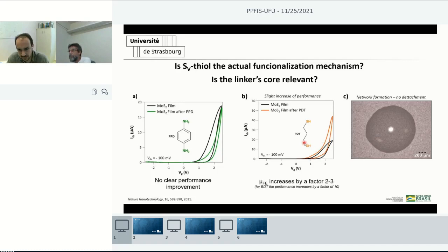And molecules with this PDT, that have the two thiols but a non-delocalized core, meaning that here you have an alkyl chain. And what we see is there is an increase of performance when we use this kind of molecule. So this molecule promotes the bridge, and this results in an increase of current. And why am I telling you it promotes the bridge? If we do the wetting experiment that I showed you a few slides back, there is no detachment of flakes, meaning that this molecule is able to put flakes together, to bridge flakes together. But the performance increases just by a factor of 2 or 3, and not 1 order of magnitude as we saw for the BDT.